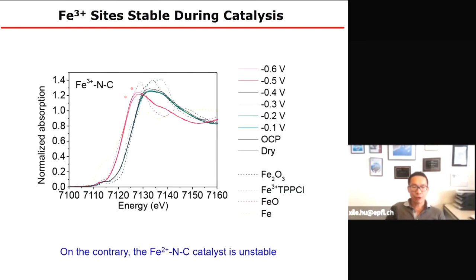We can characterize them by in situ X-ray absorption spectroscopy, and we can look at the oxidation states under different potentials. And to our surprise, without getting into the detail of this data, a lot of busy lines, we found that our iron 3 catalysts remain at iron 3 at potentials as negative as -0.5. That's a big surprise to us, because we thought under CO2 reduction, its reductive potential would reduce it to iron 2. So these are quite stable.